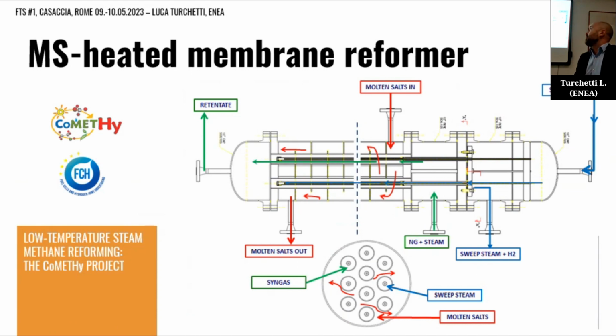This is a scheme of the molten salt heated membrane reformer that was developed for this project. As you can see here, it's basically a shell and tube configuration. It is very close to a shell and tube exchanger, where molten salt is flown in the shell side of the system. And in the tube side, you have a tube-in-tube configuration where you have an annular space where the reaction is carried out, and the membrane is an inner tube inside the reaction tube.